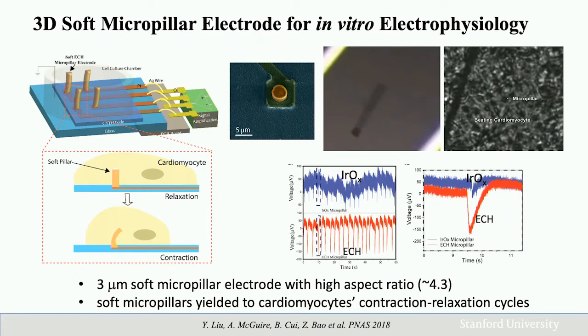So with these kinds of patterning and a very soft structure, we can now make probes that are similar to the nanowire probes you've seen earlier that Jacob made before. But these are soft probes. Soft probes that you can see can flow around with the liquid and also interface with cells.